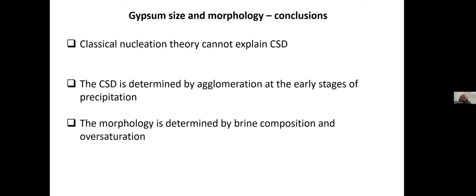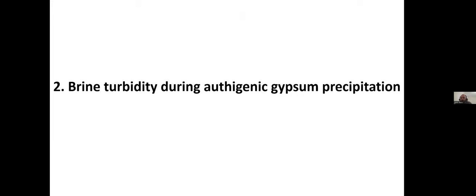So I'll just sum up this part of the talk. The classical nucleation theory does not explain the CSD formed in gypsum precipitation in these conditions. This is defined by the agglomeration, and the morphology is determined by both brine composition and oversaturation. So now I know how the crystal size distribution looks and how it develops over time. So I wanted to know how it impacts the turbidity, basically, would there be or not be a whitening?